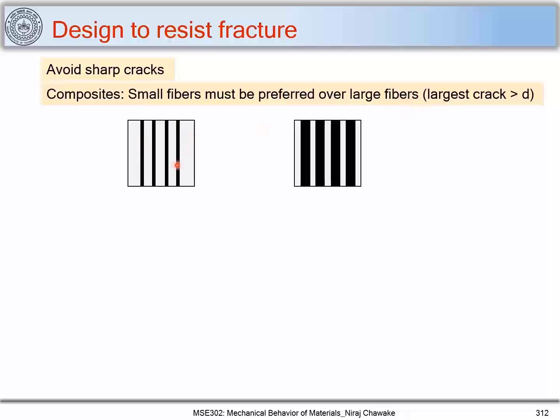So let's say you have these two conditions where you have small fibers in matrix and these are the large fibers in this matrix. So you can see that if there is a delamination happening, let's say there is a delamination over here, the crack will typically have the length of this D. So the largest crack will be greater than this diameter of this fiber. Let me write that down also. So your crack will be somewhat similar to diameter of this fiber, and thus if the crack length is higher, the material will fail at lower stresses also. That is, the fracture toughness goes down.